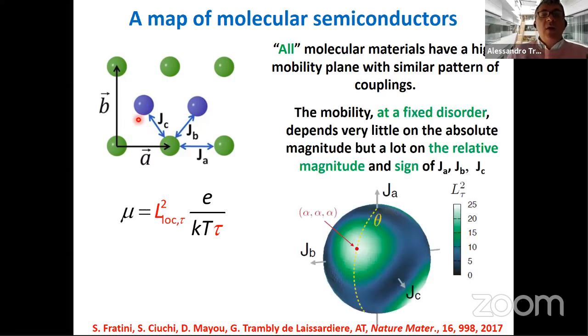So what we came up with is essentially a map, a one-to-one correspondence between all possible molecular semiconductors and points on a sphere. Each point corresponds to one particular arrangement of transfer integrals between neighboring molecules. So this point here corresponds to transfer integrals JA, JB, and JC, which are similar in sign and size. This point here corresponds to a point where JA is large and JB and JC are very small or 0. And the color on this map indicates whether the mobility is large or small.